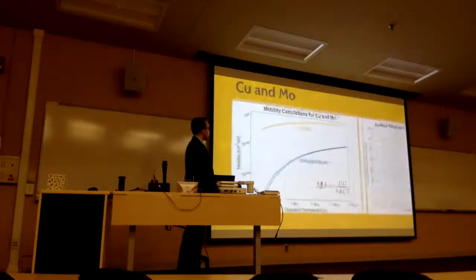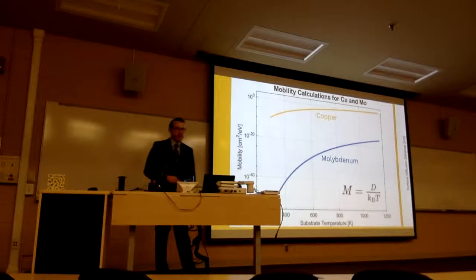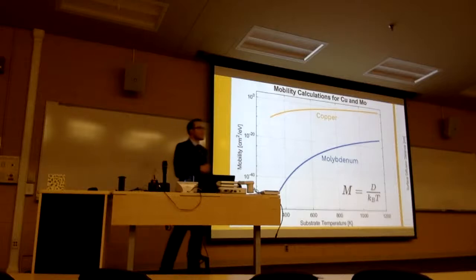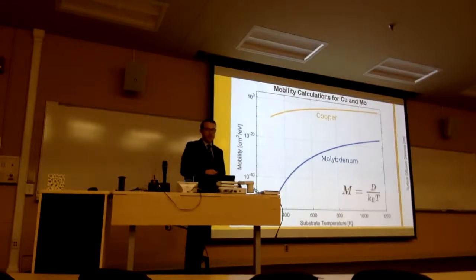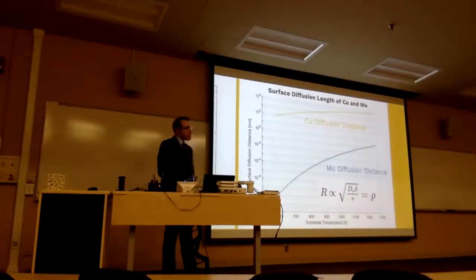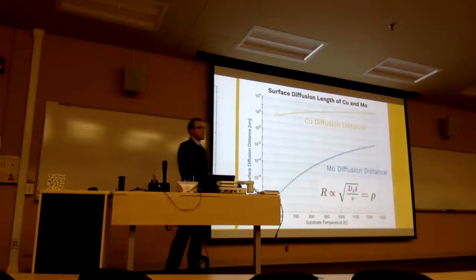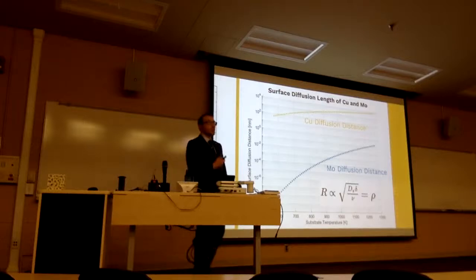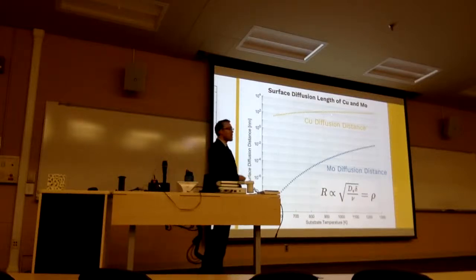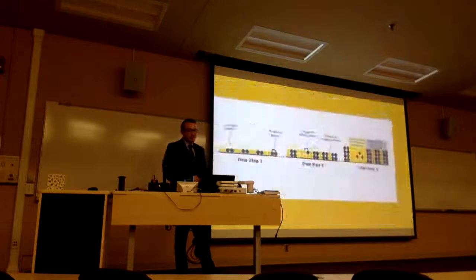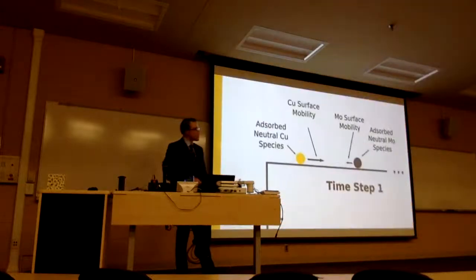What do I mean? Well, if you look at the mobility between copper and moly adatoms, you can see that copper is much more mobile than the molybdenum atoms at the temperatures that we deposited in this study. What that translates to is a diffusion distance much larger for the more mobile species, in this case copper, than molybdenum. And so schematically, what we think is going on is that at early stages of the deposition, you can see these two adatoms on the surface, one much more mobile than the other.